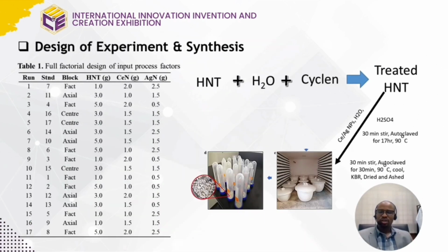So in our methodology, we deployed a design of experiment where we generated a series of different combinations of the nanoparticles. These nanoparticles were then combined with water and Cyclen to pre-treat the nanomaterial. The nanomaterial was subsequently treated with other reagents, and then a solid product was obtained.